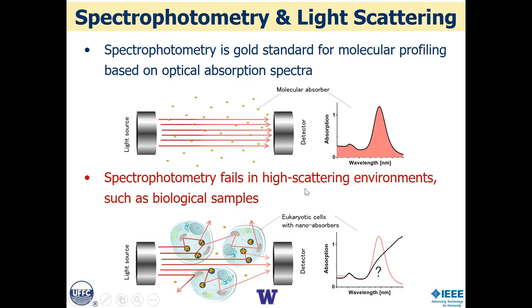However, spectrophotometry fails in a lot of important cases of interest, where you can have high optical scattering as well. And here's a case which I'll use as the example to show the power of doing spectrophotometry a different way. That is, if you want to look at these same nanoparticles, but in cell culture, and see how those nanoparticles are trafficking through individual cells. Once the nanoparticles are integrated with the cells, this is a very complex optical environment, which can scatter light out. And so you will get simple optical absorption measurements which are nonsense and don't tell you anything.